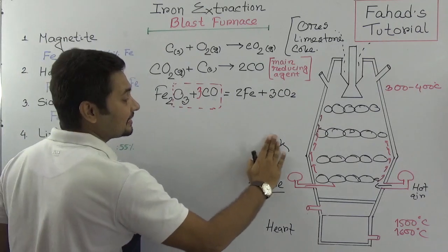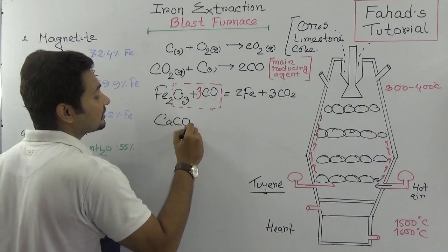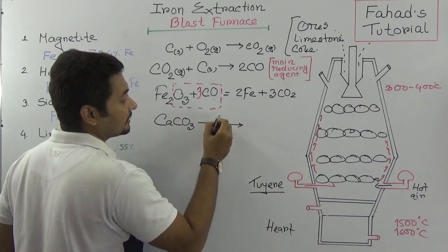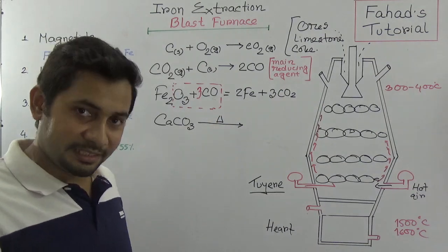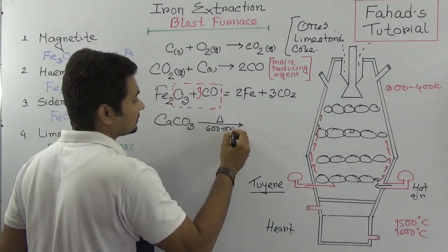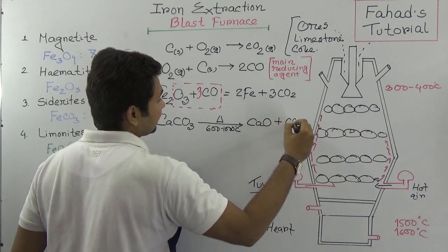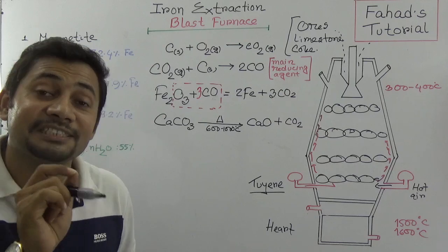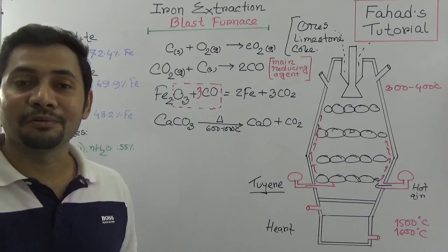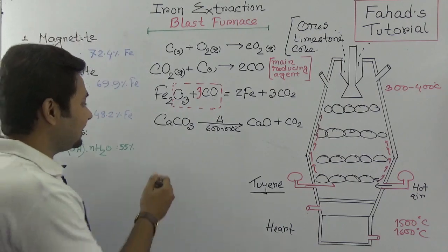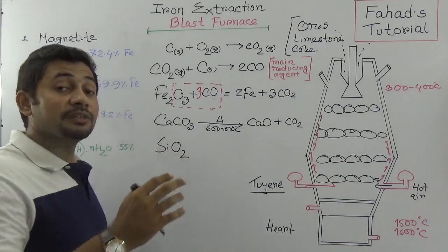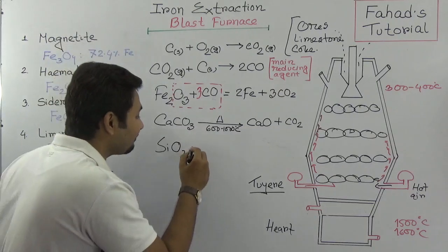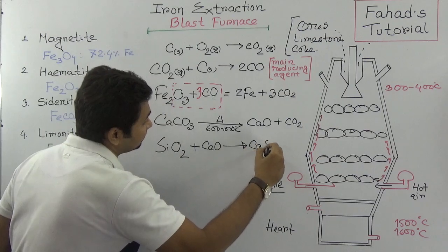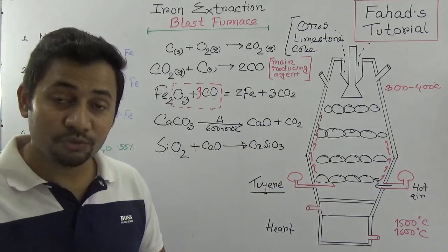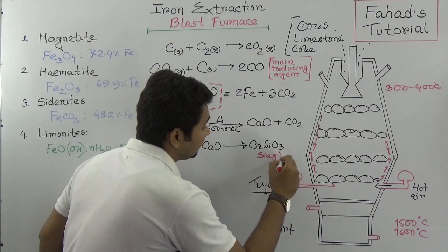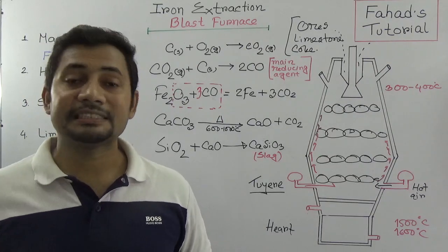Then the main important thing you must remember is that limestone, that is calcium carbonate, is broken down. That is called thermal decomposition, which takes place at about 600 to 1000 degrees Celsius, and it produces calcium oxide and carbon dioxide. Now this calcium oxide will play another role: it creates the slag. The silica, or the sand, is mixing with that iron ore. Now it will react with calcium oxide, and then it will produce calcium silicate, which is actually a slag. So this is a slag that is simply not required. So calcium silicate, we don't need this.